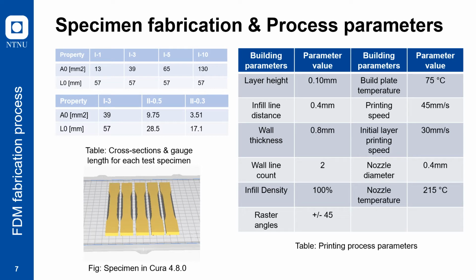And the table on the right side is the printing process parameters, some major important parameters, like the layer height. We used 0.1 millimeter. That's the best layer height we can achieve so far with this printer with good quality. And the infill line distance is 0.4, and the infill density is 100%, because we try to infill as much as possible to keep the mechanical property similar to the solid part, but at the same time maintain the quality of the specimen. Also, the raster angle is plus minus 45 alternately for each layer.